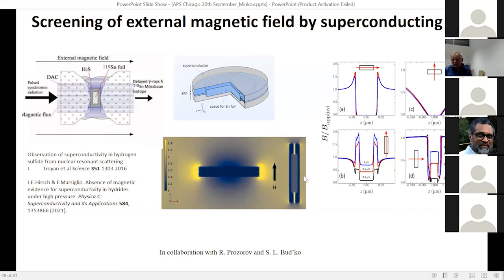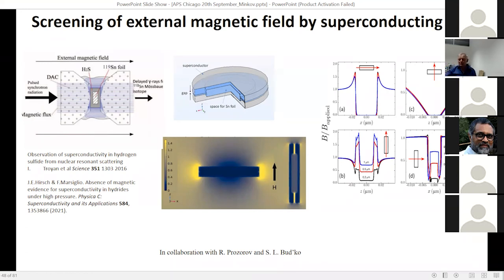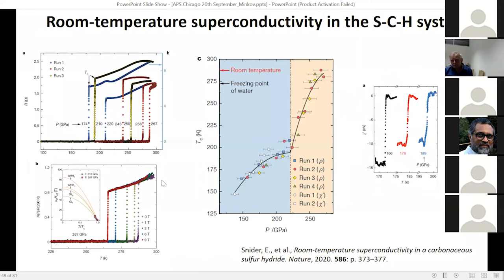This NRS experiment was severely criticized, but Prozorov and Bud'ko did precise numerical calculations: they modeled the tin film surrounded by H3S and asked whether the magnetic field would be inside. The calculations show that no magnetic field is inside the sample. They even considered a more complicated case with a sub-micrometer slit — even then the magnetic field inside should be zero. So the NRS result is strong evidence for superconductivity.